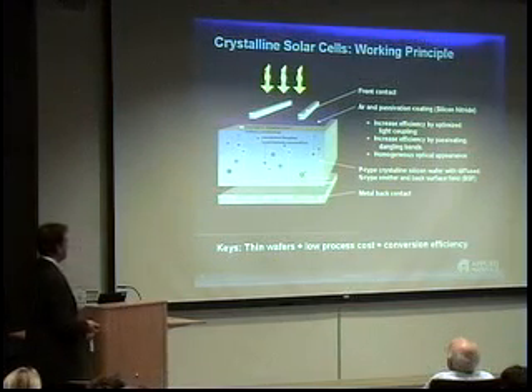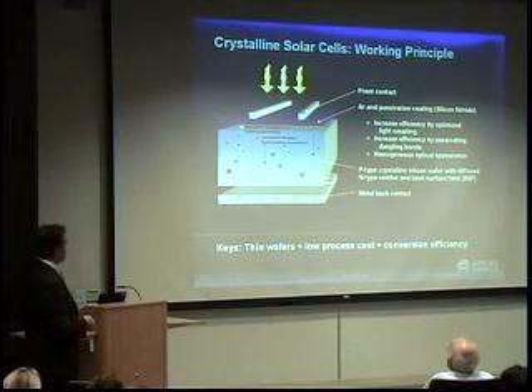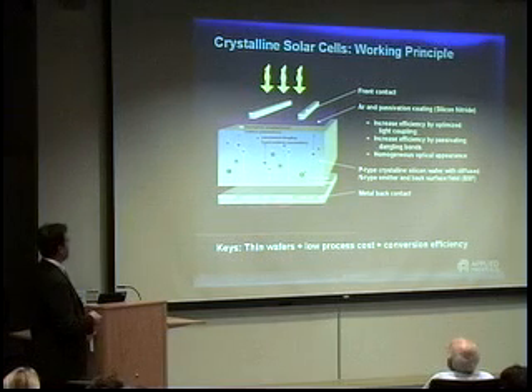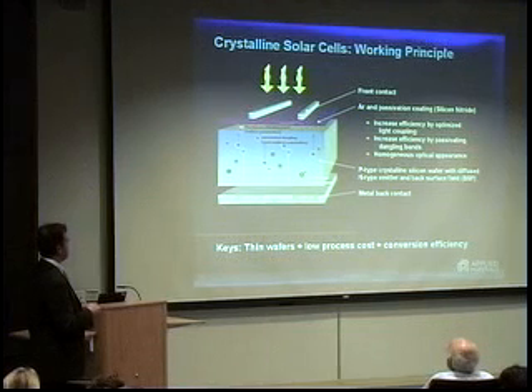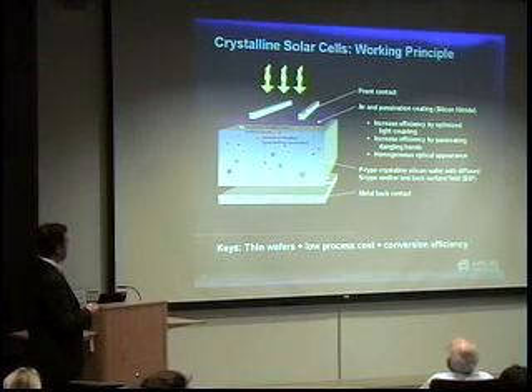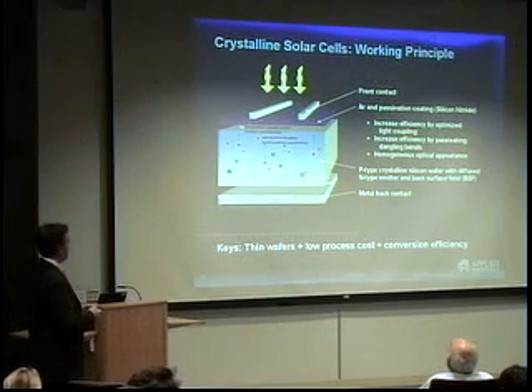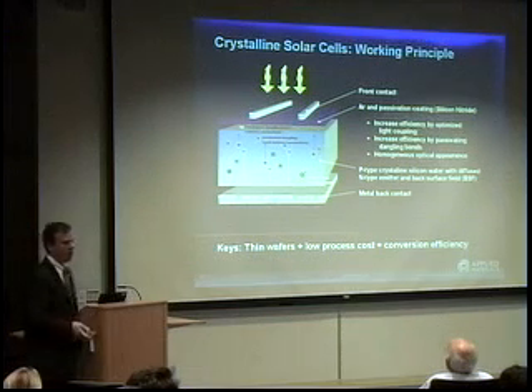This is how a solar cell works. This is the simplest kind, where you have contacts on the back and the front. You have an anti-reflective coating that sucks in the light, that also passivates the surface so you don't lose a lot of the electricity at the surface. Light comes in, generates electrons and holes. They migrate to either side, and you get voltage and current out of the device.